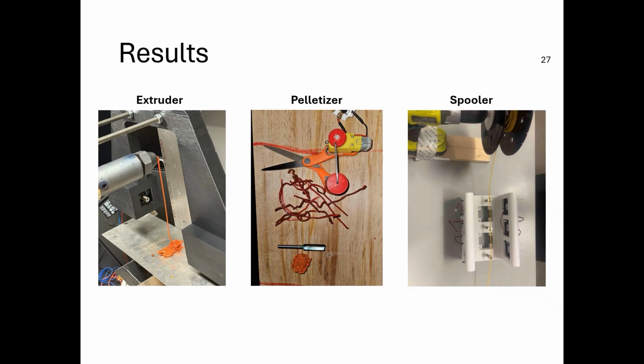To do so, we created our new motorized scissor cutter, which uses a crankshaft to open and close the blades to cut the filament as it comes down. However, it was not able to cut the material consistently enough to start the next extruding process, as you can see here, where the router bit was not able to cut the filament at all, and the scissors did cut the material, but it would either bend it or deform it and then cut it, creating long pieces that were not usable for the final part.